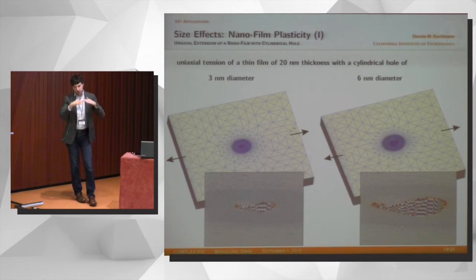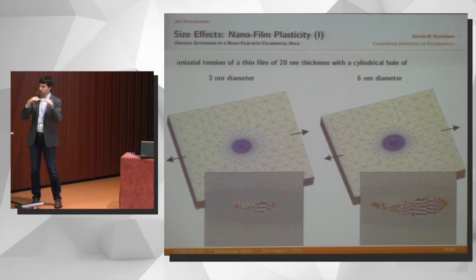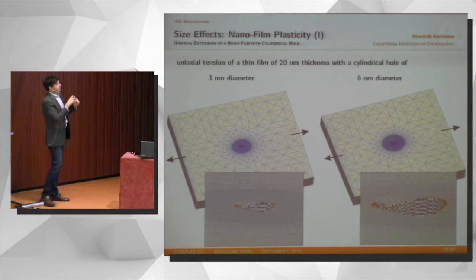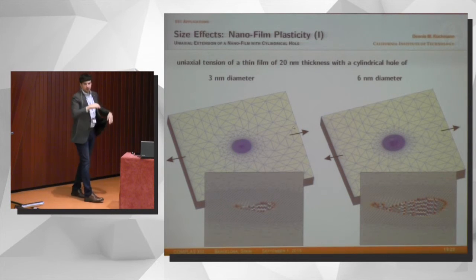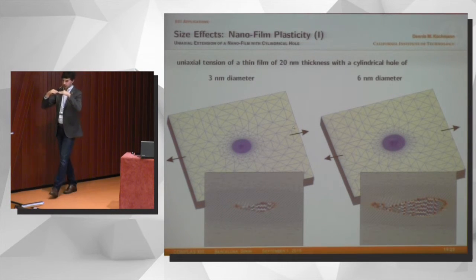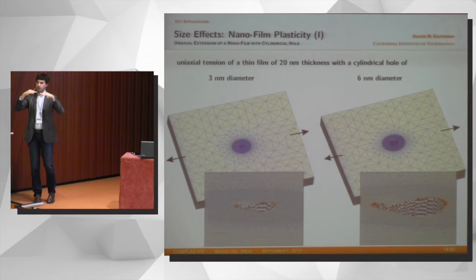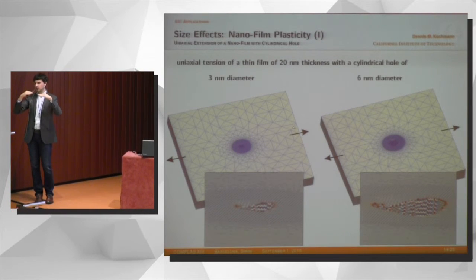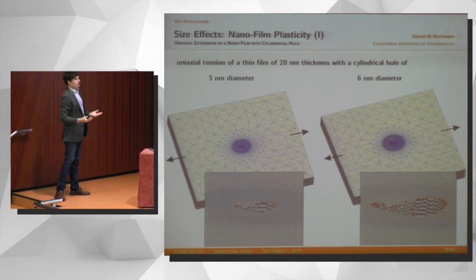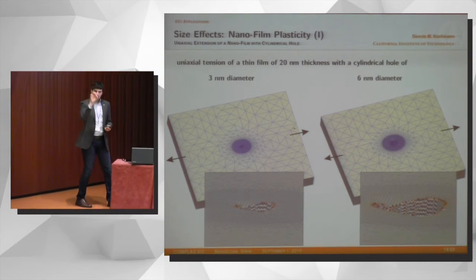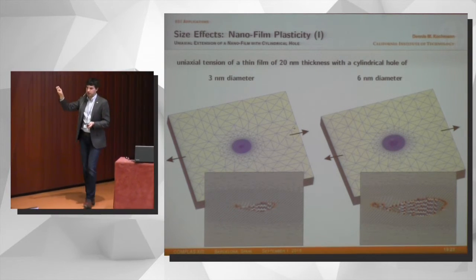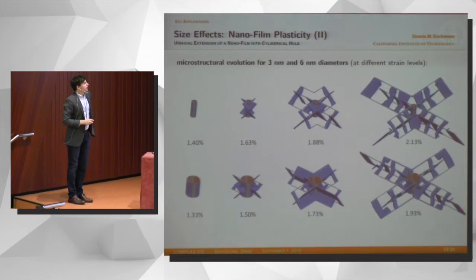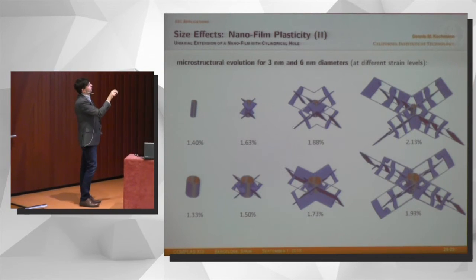And also, because we use this special summation rule, the surfaces are accounted for, which means this simulation actually feels that there is a free surface. In atomistics, that matters because you have surface relaxation effects. The surface has a different elastic modulus than the inside, and that's automatically accounted for by having these quadrature atoms on the surface that feel the difference in energy. Again, this is what the dislocation loops look like.